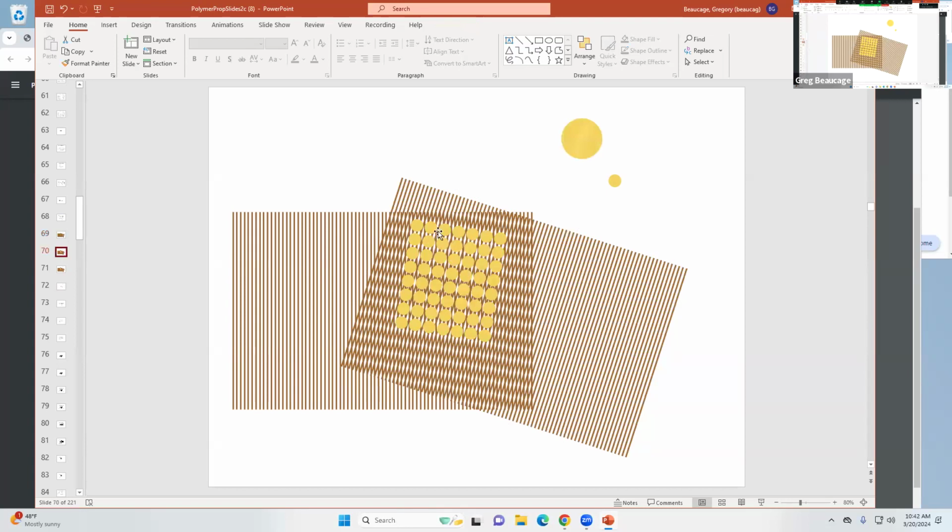So you have to have material at that fringe pattern. If it's a crystal, the atoms have to be lined up along those fringe patterns to get a diffraction peak. That's going to be a rare occurrence if you randomly throw a diamond, a crystal, into the X-ray beam. You can grind up the diamond into a powder, and then some of the grains will meet that condition and you get the diffraction peak, but you've ruined the diamond. Or you could take the diamond and spin it around in space, so you do a rotation of the crystal, and sometimes it'll be in that condition and get the diffraction.